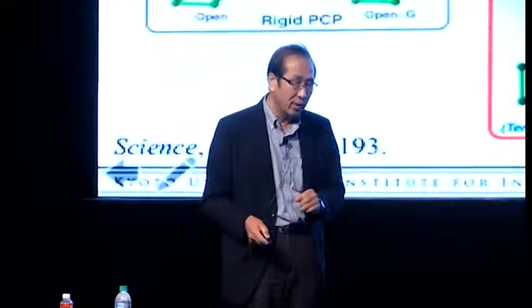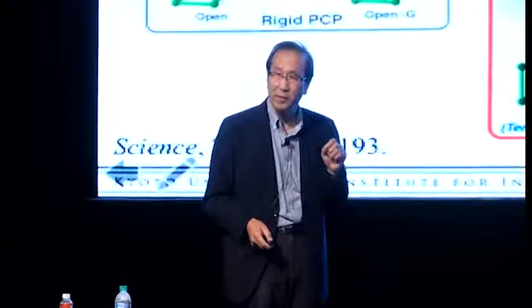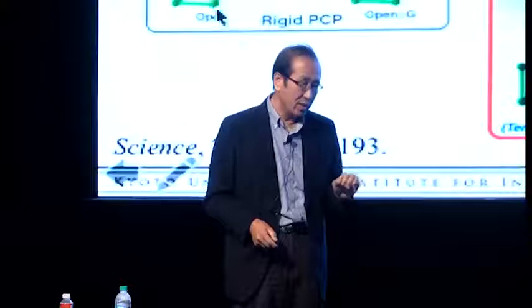So this is a sort of shape memory effect, completely different from the bulk state. So this is also a discovery. And this is just a summary. If you're synthesizing certain compounds, you have a chance to change the crystal size for the discovery of new properties. From bulk scale, this is the closed form and open form like this. But in the intermediate case, we can observe the shape memory. The structure is still maintained. And in the nanoscale, for instance cage compound, the structure, of course, is maintained, but this is just intermediate properties. So the downsizing is very important. From bulk scale to the intermediate, mesoscale phase, and also the nanoscale phase, we have many chances to see new properties.